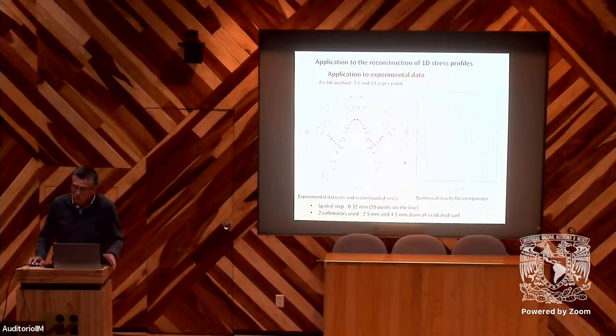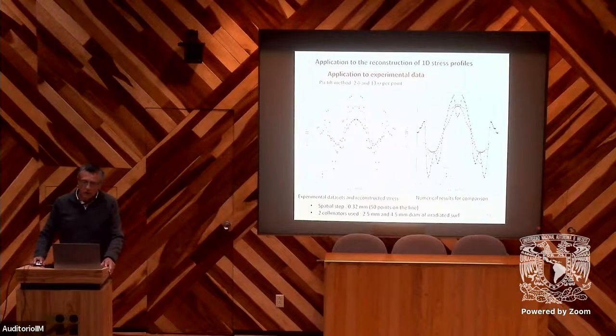We use our method for this, and this is what we measure by X-ray diffraction. For the small size, we have the blue curve, and for the bigger, we have the red curve here. And from the two, you see here the black line. This is the profile reconstructed from the two. And then we can compare this profile, the black one, to our reference obtained by calculation. And also we can compare the measurement directly to the average profile obtained by calculation.